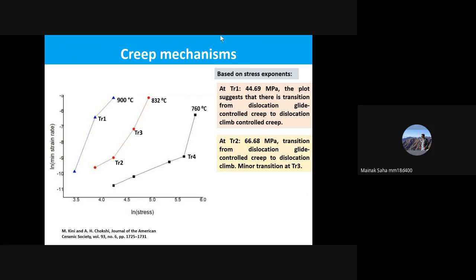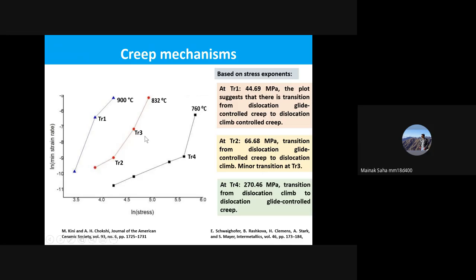But however, there is a minor transition at TR3, and the stress exponent here and here do not vary to a huge extent. So definitely no such statement could be made for the TR3 transition. But now when we look at 760 degrees centigrade, we find that the transition temperature, TR4, is comparatively at much higher stress levels, at around 270.46 MPa.